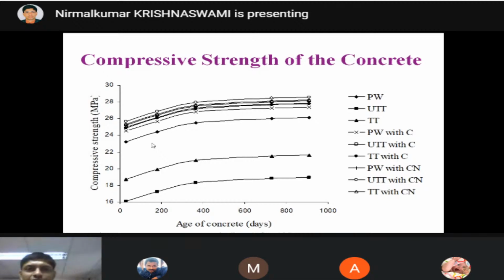After testing the loss of weight due to the chloride attack, the same specimens were tested for compressive strength. This particular thing is our benchmark. Maximum it is around 26, minimum 25. When adding the admixtures, minimum 25 and maximum it shoots up to 29.